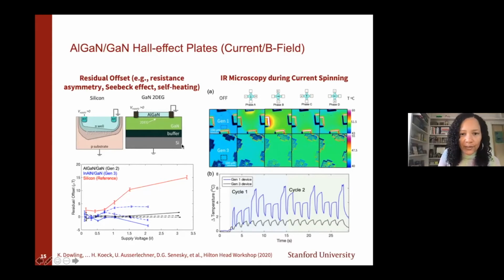You have to make sure you have good alignment when you're fabricating your devices. And so what we studied with IR microscopy is the thermal gradients across our different generations of our devices. This is first gen where our contacts were not very well aligned, and we can see here a larger thermal gradient. This is shown in the blue, so larger DTs across our device, and that's translated to higher offset. Gen 3, we perfected our alignment, a better alignment, but still there is some, it's hard to see in this image, but there's still some thermal gradient across the device. And that again translates to the offset.